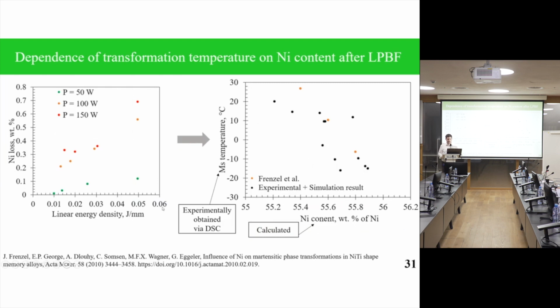And also we can take experimentally obtained transformation temperature that was measured by differential scanning calorimetry. And this received dependence is actually close to the dependence that I showed in the beginning, that was verified many times. So by this, we can conclude that the main mechanism of shift in transformation temperature, or local adaptation of functional properties, is the different kinetics of nickel evaporation that was calculated by this simulation.